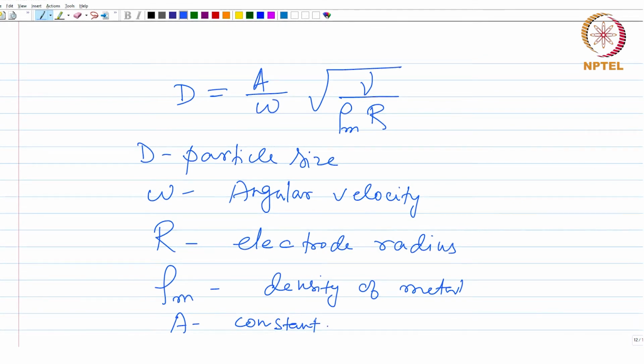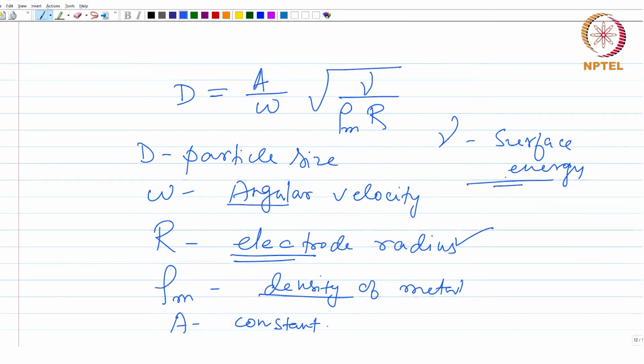Right. So, here we are talking about the rotating rod method in particular, because in that case the rod itself is used as the electrode which is being melted. Right. So, you can see apart from the size of the rod, the other parameters which will affect the particle size are the angular velocity, the density of the metal, and also the surface energy gamma. Right. So, these are the main parameters or main process variables which will control the particle size.